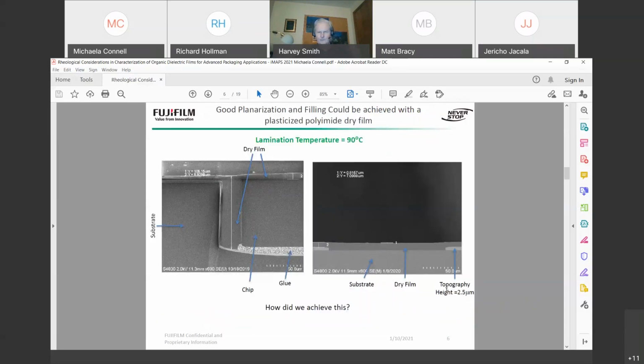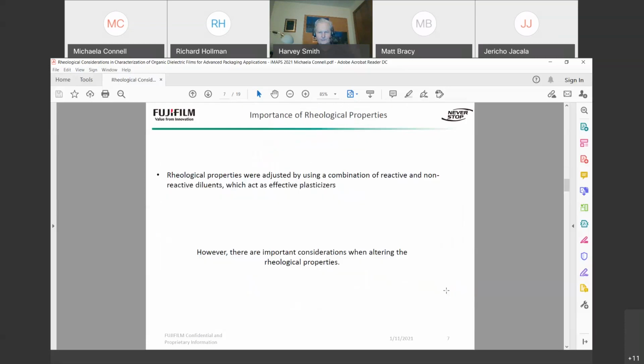And in this example, you can see that on the left, the same embedded chip structure that we saw in the previous slide has been successfully filled and planarized. And on the right, you can see that the dishing has been reduced to 0.8 micron between the 2.5 micron high topography. And these were achieved at a lamination temperature of 90 degrees Celsius. So how did we achieve this?